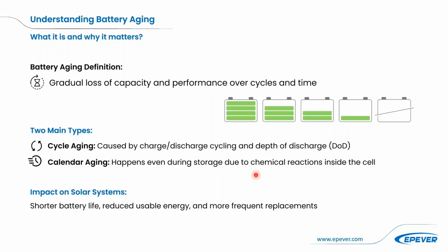So before we talk about the common mistakes, we need to understand a criterion that is called battery aging. Aging is simply the gradual loss of capacity and performance. And there are two main types of aging. One is cycle aging, which happens each time the battery charges and discharges and is worse with deep cycles. So the deeper the depth of discharge, the more aging you have in your system.